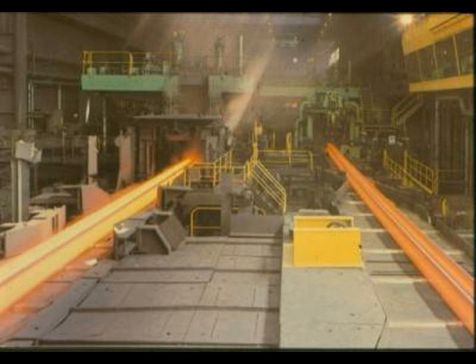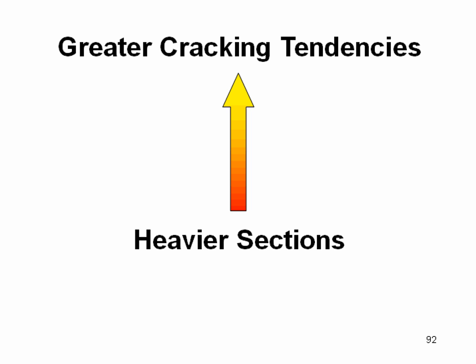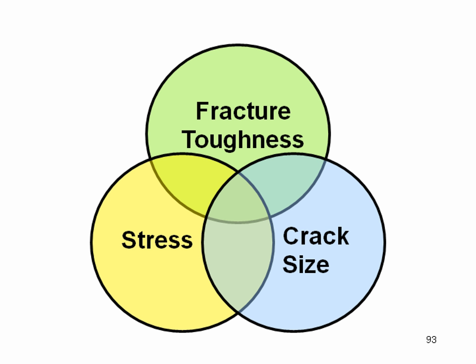Now, for these reasons, and even perhaps more we haven't identified, when we get to heavier sections, we have a greater cracking tendency. And that's consistent with your experience, I suspect. When you're welding on heavier steel, you're more likely to see cracking than when you're welding on lighter weight material. Now, when we're talking about cracking, we are talking about a fracture problem, and fracture is controlled by fracture mechanics.